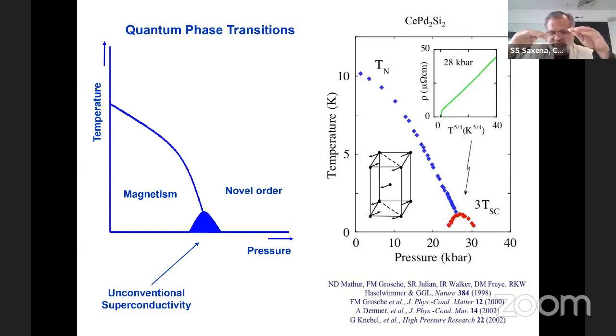So there's scattering. Since there are not just electrons left and it's not thermal, something else is there, which is this quantum fluctuation, you can call it a magnon rather than a phonon, and your electrons scatter from it, and that in a sense also creates an attractive potential. Once your electron scatters off this fluctuation, they both lose energy, and the physics becomes that of dissipative modes in the system. This is an important consideration. Basically, the fluctuation dies down immediately, and an electron loses energy. If you want to think in a pseudo-classical way, you have thrown a pebble into honey, and it deforms, but it cannot propagate out. Since it cannot propagate out, it starts to retract.